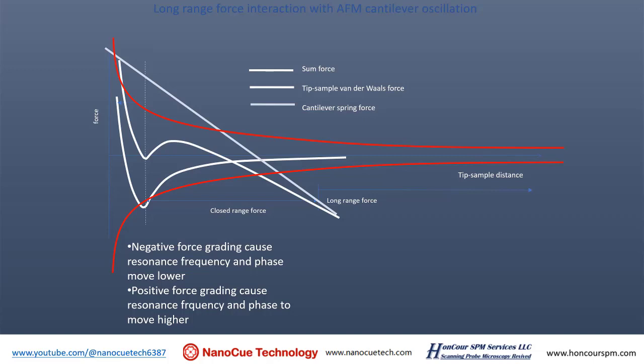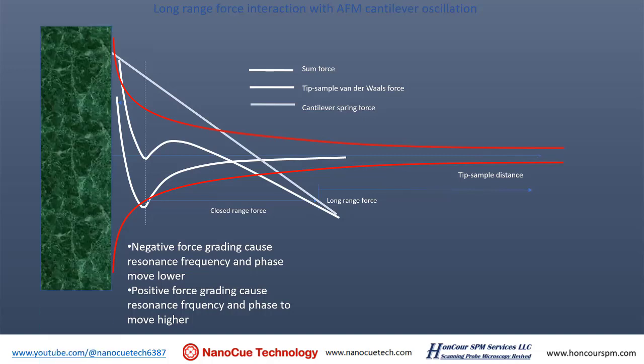Suppose the tip is approaching the sample. The tip-sample distance is within a nanometer to 10 nanometers, so the tip is oscillating in that short range force region. The resonant frequency of the tip is influenced by this short range force — and that is what we call tapping mode, or non-contact mode. This force allows the tip to interact with the sample and obtain topography information, because this short range force tracks the surface topography up to nanometer resolution or even sharper.